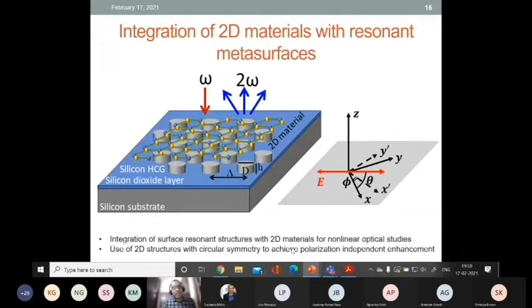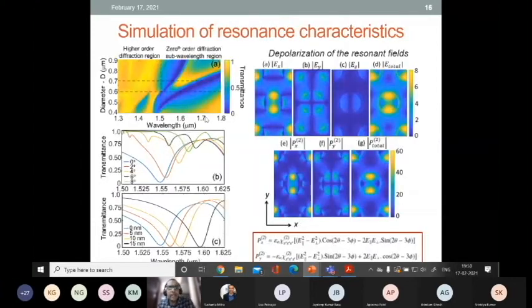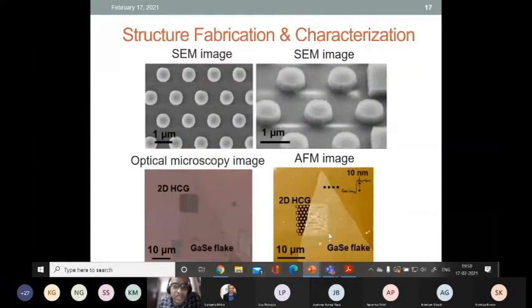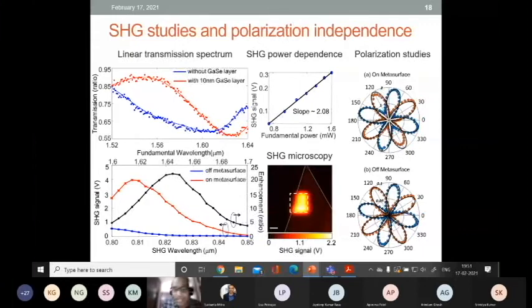So we started venturing in this direction where we looked at this kind of hexagonal underlying lattice, and then we transferred a multilayer gallium selenide, which is our nonlinear medium, to look at second order nonlinear effects in this world. And we designed these cavities to have a resonance in the telecom wavelengths where we had efficient excitation sources, and then tried to understand the polarization and the light emission properties. And these are some examples of the structures we have fabricated and the transfer of these 2D material flakes on top of these structures.